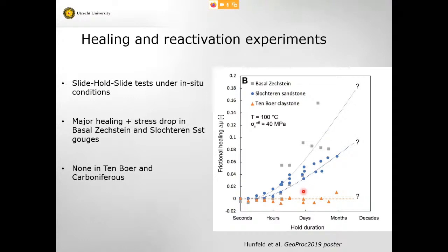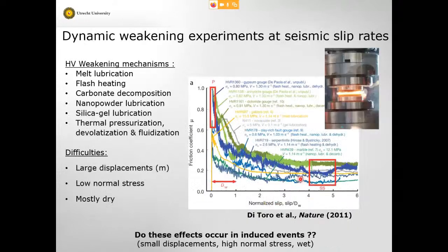Of course, if you re-slide this material, the rock loses its strength. You get a bang. So this is also a measure of the seismogenic potential of these materials. It tells you again that the carbonate anhydrite at the bottom of the evaporites and the sandstones have potential to produce accelerating slip when you reactivate a fault in those materials.